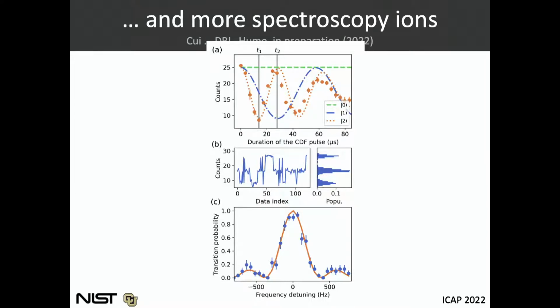So here's a picture where I'm showing these different fluorescence levels from the magnesium ions that correspond to, well, 2 aluminum ions in the ground state, 1 aluminum ion in the ground state, and 0 aluminum ions in the ground state. And this is a scan over the line with these 2 aluminum plus 2 magnesium. Okay.